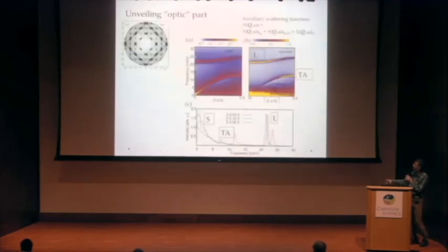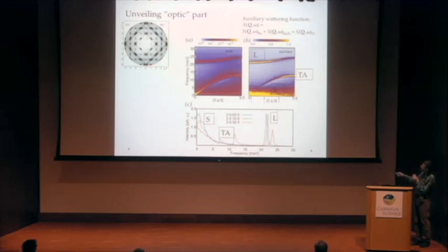And then I get the usual dispersion, which involves the acoustic branch and the optic branch. This is the last mode, the higher frequency mode, TO2 mode, if you wish. And the soft mode is here, it's the Slater mode, which is somehow, by some trick, making the higher contrast here. This is what you really measure, this is what we calculated. And this is done because we want to look at what the spectrum is at that point, for example, close to the zone center.